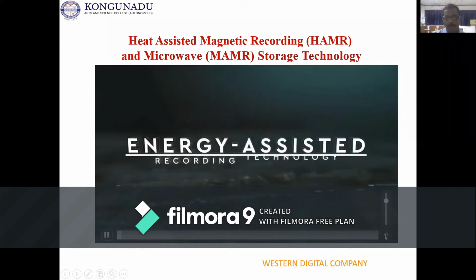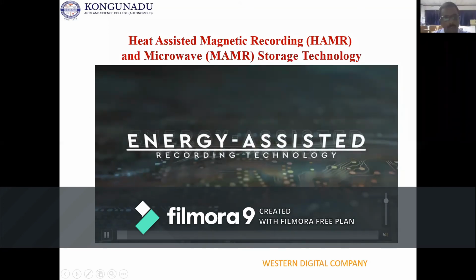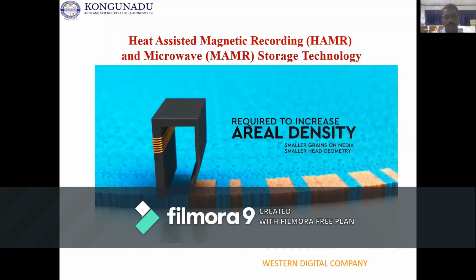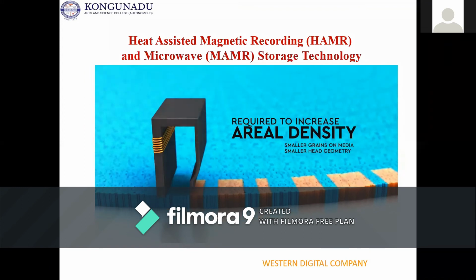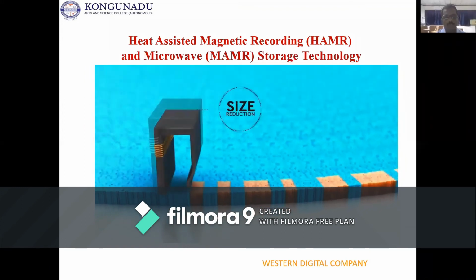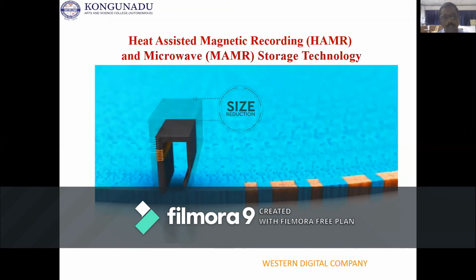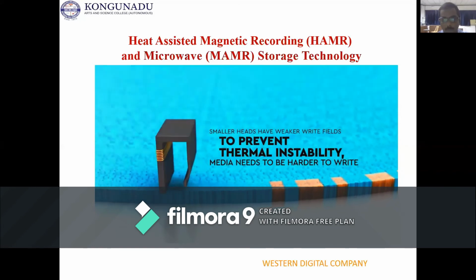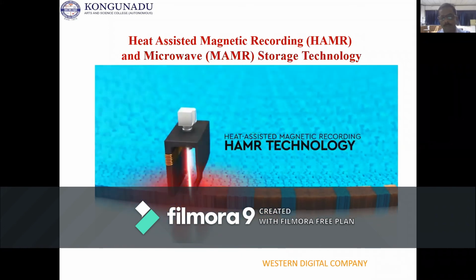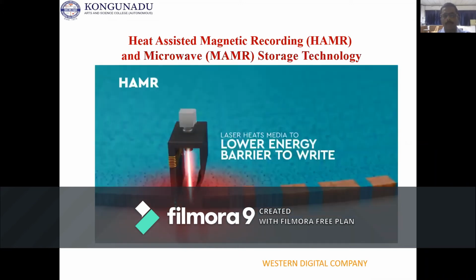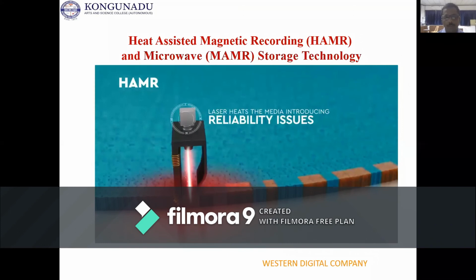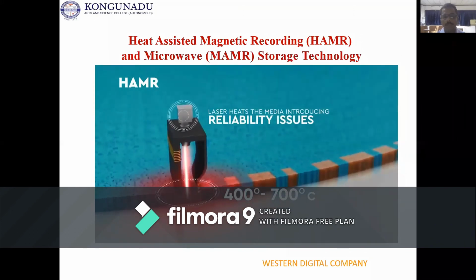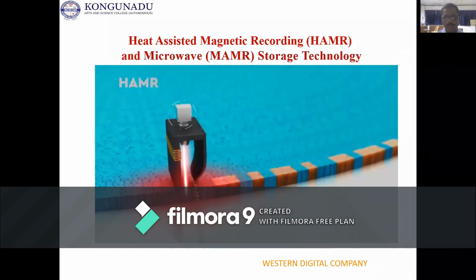I will put on a small video. Please, you can see. So this is how a normal magnetic hard device is used, where the areal density is very high. When you increase the areal density of this magnetic read head, it will have a thermal stability problem. So people have come up with heat-assisted magnetic recording and microwave magnetic recording, where a small laser goes through the magnetic layer and manipulates the magnetic spins, and this can be used to store the data.